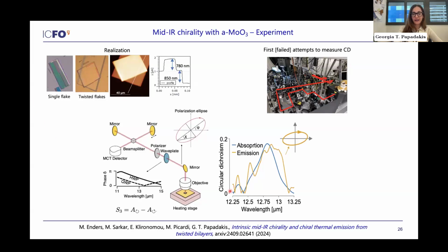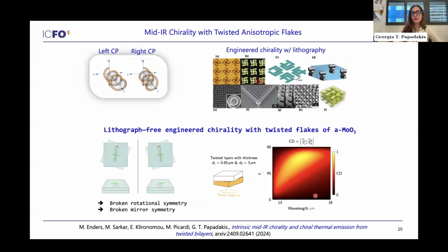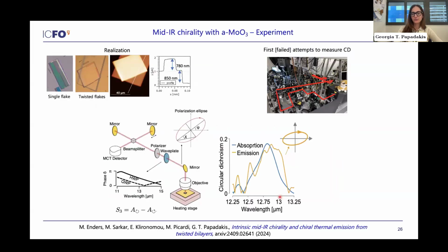Nonetheless, we have been able to actually very accurately measure the thermal emissivity, which is shown in the yellow line here. And this is actually the ellipticity of the beam that we get. So you can see that it's not perfectly circular, it's actually elliptical. Nonetheless, this is an experimental proof of generation of circularly polarized light that has a specific handedness, thermal generation of such light. And the blue curve is simply the circular dichroism that goes up to 0.2 because, of course, we don't have these very large devices to get all the way to the theoretically expected result.